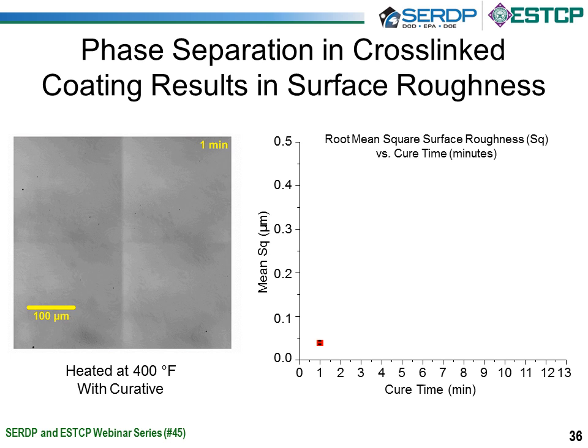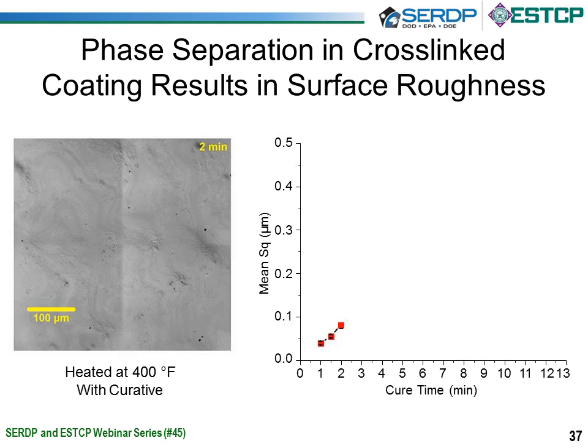In the graph on the right-hand side, you can see we start off at 1 minute. The root mean square shows a very low surface roughness, and this is what is to be expected given the fact that we've heated the polyols with the curative at 400 degrees Fahrenheit for only 1 minute. If we then go to slide 37, we see that phase separation continues. At 2 minutes, surface roughness is increasing, but still we have a continuous film. And it's very important to illustrate that we must afford a continuous film that completely coats the surface in addition to providing the topical surface roughness to achieve the low gloss.